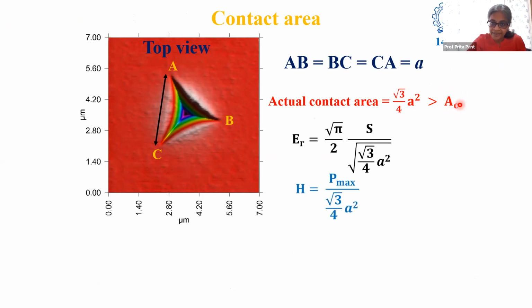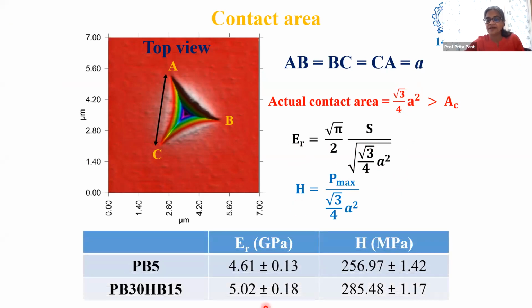Okay, and then Prakash did these measurements for several indents in samples with various levels of cross-linking. And instead of using the standard method, we simply said, look, once we've measured this A, this is the contact area. I can calculate the contact area directly like this, and I can calculate the ER and the H. And if I do that, then these are the values that I get. My less cross-linked sample indeed has a lower modulus. My more cross-linked sample indeed has a higher modulus, and the same goes for hardness. And the difference is definitely not negligible.